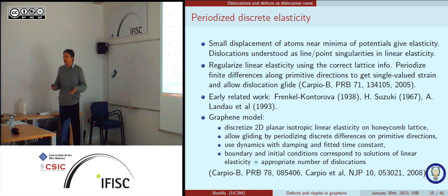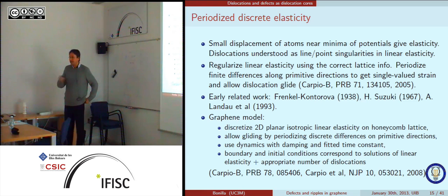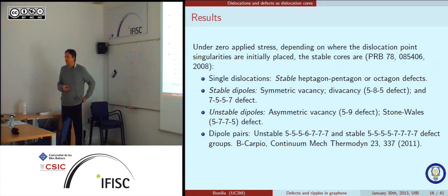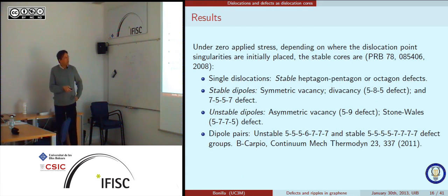So you have some functions, you use them to put the atoms on the lattice and use the same thing as boundary conditions. And now, since it's all linear elasticity, you can put as many of these dislocations as you want and see how they evolve. Okay? So that's the theory that we did in these papers. And we found a bunch of results.